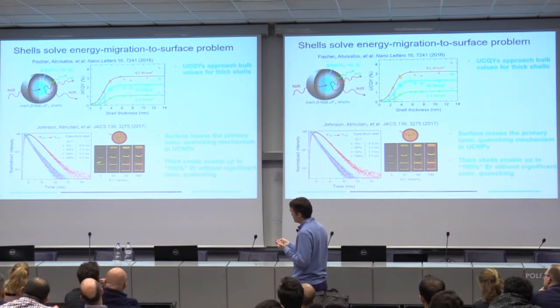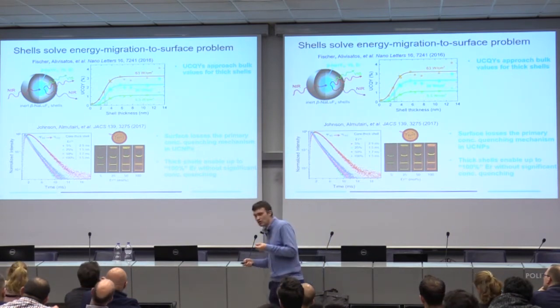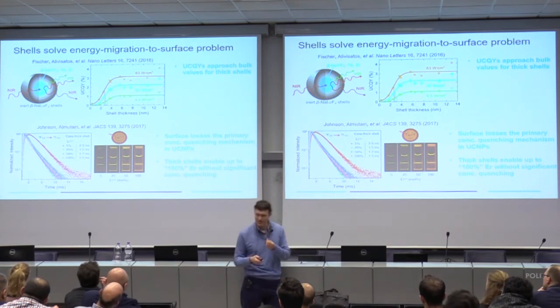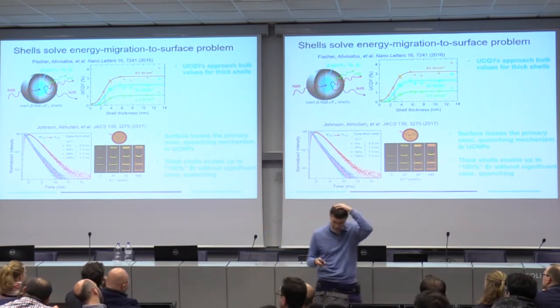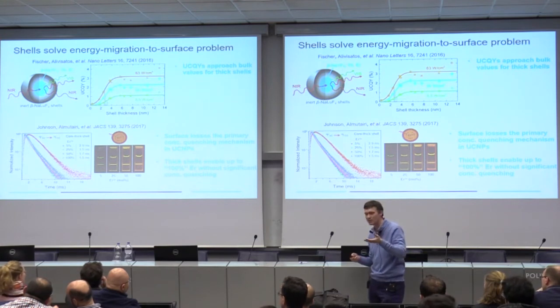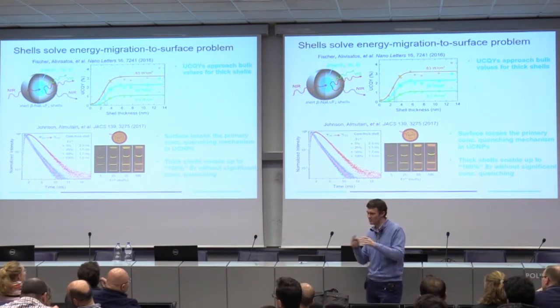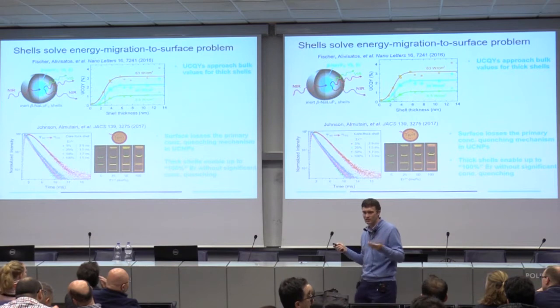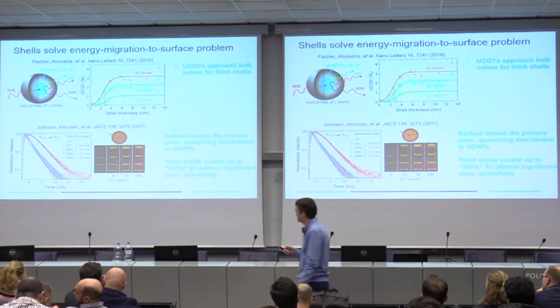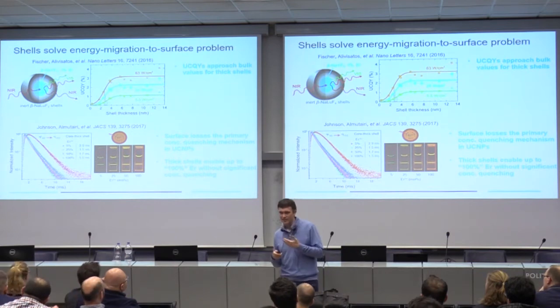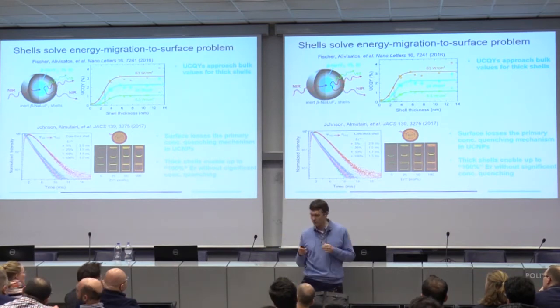Or here they really did go up to 100% erbium. And what they showed is that the main component of this concentration quenching in these materials is actually losses at the surface. When they put the shell on, basically all the supposed concentration quenching went away, which was pretty exciting. So in fact, now we realized we didn't have to listen to the old rules at all, which was nice.